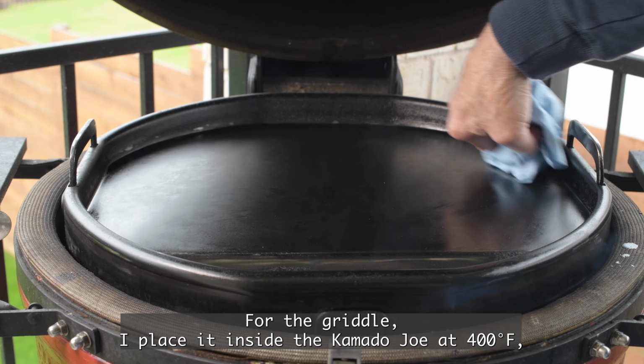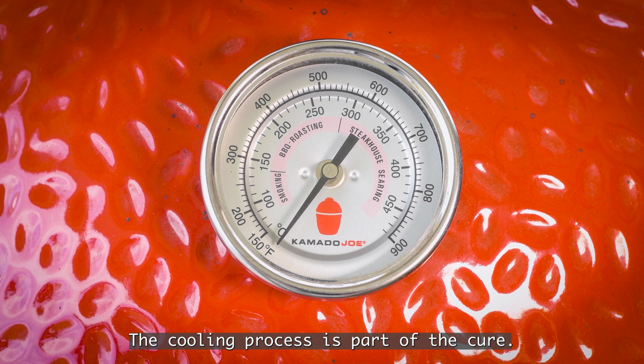For the griddle, I placed it inside the Kamado Joe at 400 degrees Fahrenheit in direct heat for 90 minutes. The griddle was just too big to fit in my oven. For the large skillet, I used the oven. Same temperature, same time. The oil polymerizes at sustained high heat and bonds to the metal surface. Let the piece cool completely before you handle it. The cooling process is part of the cure.